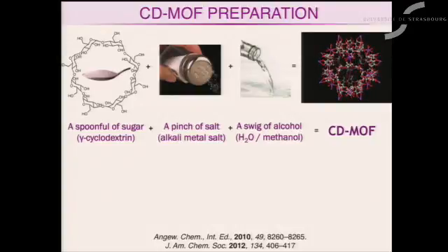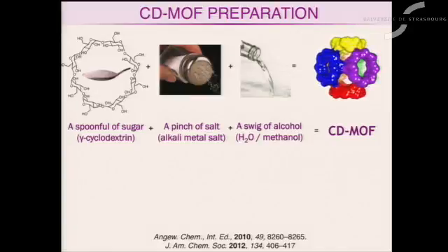And it's built up of cubes, body-centered cubes, where you have gamma-cyclodextrin linked through their primary hydroxyl groups with potassium ions to join these 6 cyclodextrins together. And then they are linked through the secondary hydroxyl groups on the sugar to their neighbors, so that you get this extended structure, again, by potassium ions. Here's another colorful representation.